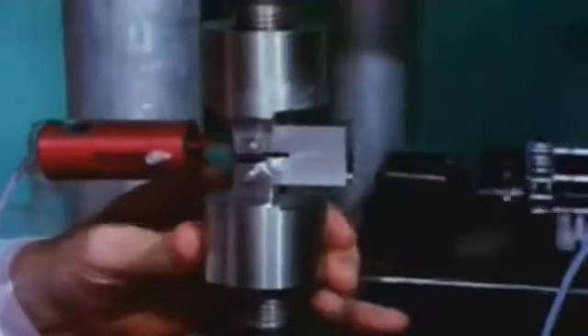For example, a section from a high-pressure pipe suspected of being liable to stress corrosion cracking was tested. A sharp notch was cut into it, and then a fine crack induced. The end of the crack is marked with a scored line. Put in tension, the opening of the crack is measured with a transducer. In a non-corrosive atmosphere, the crack opens slightly as the load is applied, but does not grow any further. When the corrosive is introduced, the crack starts to grow. Eventually, assisted by corrosion, the specimen breaks under a load it had previously withstood.